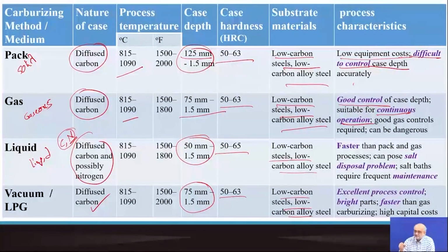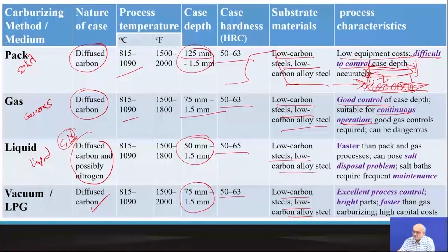So if it's a gaseous atmosphere, let's say this is the furnace and you have a conveyor belt through which your sample is charged and is allowed to be retained inside the furnace for a certain period of time at a given temperature, and then is withdrawn from the other side. So during this residence time, the component goes through a thermal cycle and gets carburized and then comes out. So this can be a continuous process. This is the only carburizing process, gas carburizing, which can be a continuous process. So that's a big advantage.